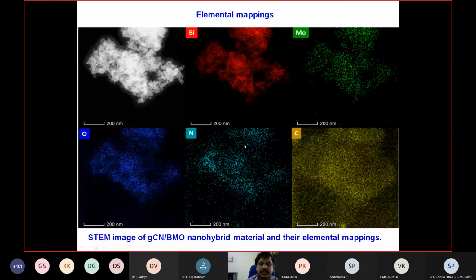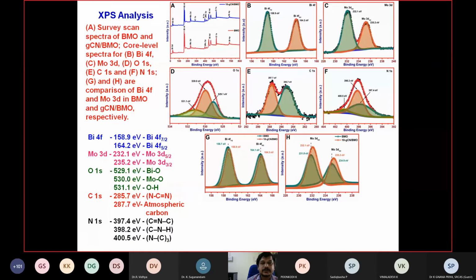Then we have taken the elemental mapping through the STEM image. We have confirmed that various elements are present in that nanohybrid material, especially bismuth, molybdenum, oxygen, nitrogen, and carbon. Those things we have confirmed from the analysis. Then we have done the XPS analysis to see the functionalities. We have seen bismuth, molybdenum, oxygen, carbon and nitrogen. All the core level spectra were recorded and confirmed the oxidation states in that nanohybrid material.